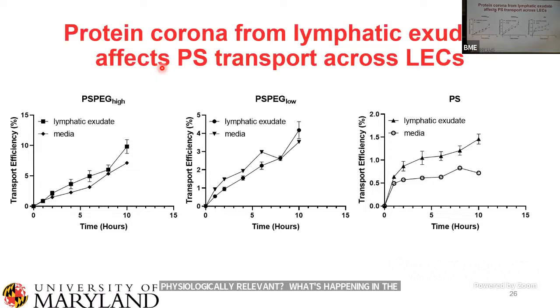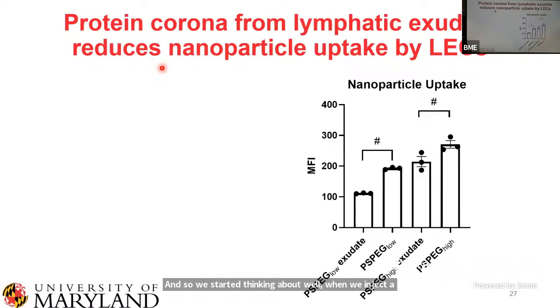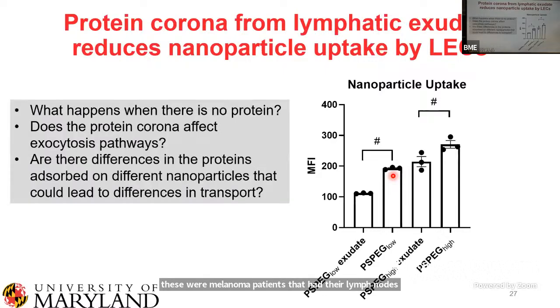Now, we also were really interested to try to understand, okay, so transport is the same, but what about things like uptake? Really interestingly, we saw that when we incubate those particles with exudate, we see a reduction in uptake. You can see in both the low density pegylated and the high density pegylated particles, there's a reduction in uptake at 24 hours compared to the ones that were just in media. So there's a lot of questions. Like I said, my grad student just collected this data in the last couple of weeks, so we're still asking a lot of questions about what's going on here.